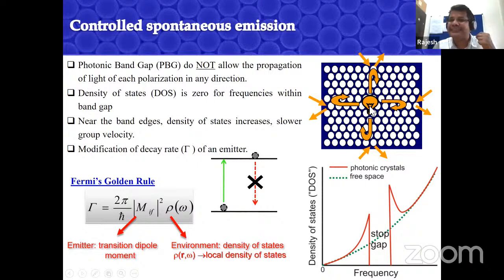And if you calculate the photon density of states, like the electron density of states you studied in condensed matter after the band gap theory, at the band gap the density of states goes to 0. This is what you studied in condensed matter. Similarly, here also you have a band gap, but at a different wavelength scale, and you expect the density of states to also be 0. So if there is no periodicity, the density of photon states has an omega squared dependence. And because of the band gap, you get a 0 density of states.